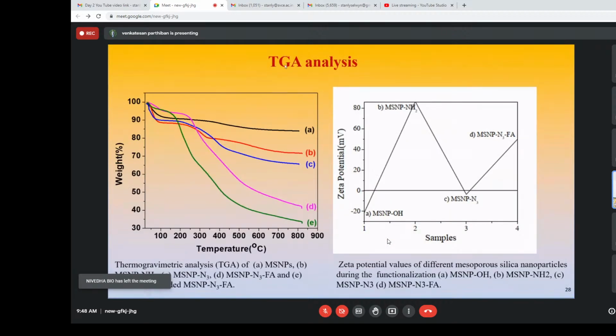Further we check the weight loss in the TG analysis. So we can see figure A is only the mesoporous silica nanoparticle. Further, as we attach the different functionalization, we can see the weight loss and drug loading ratio is also decreasing, because of figure D and E. The reason is that we added some fluorescein dye to load as a model drug. So we can see the drug loading here also.